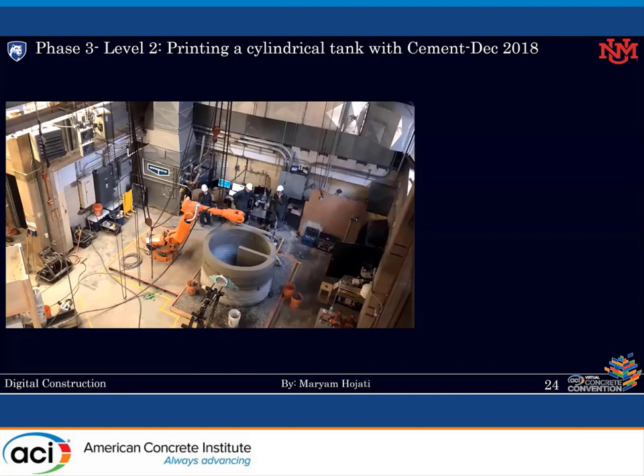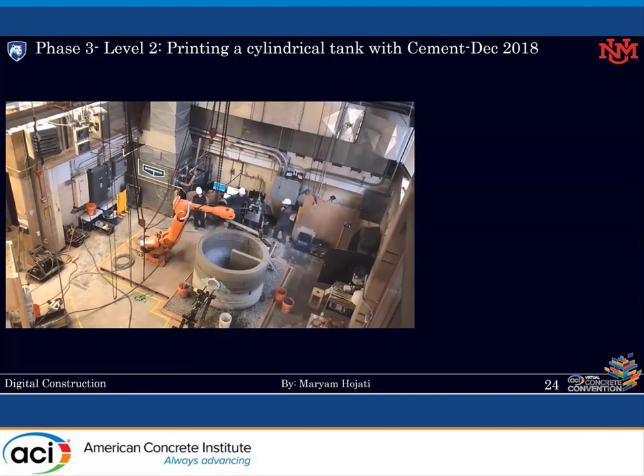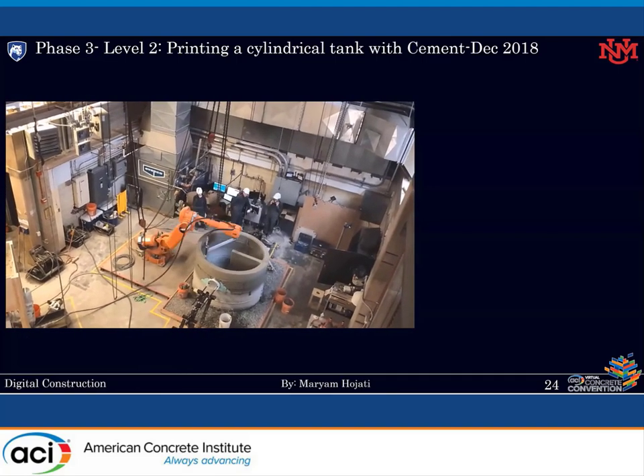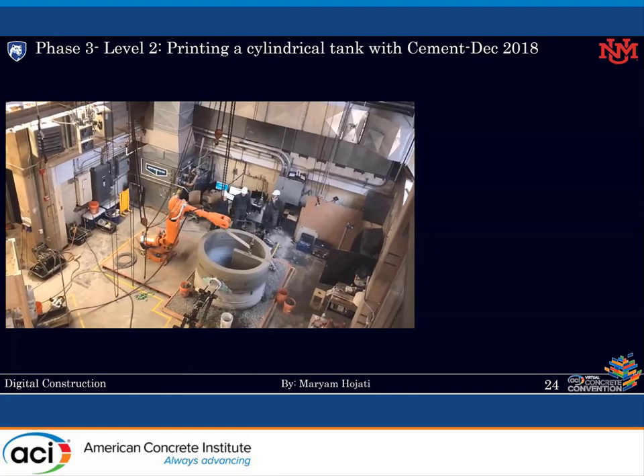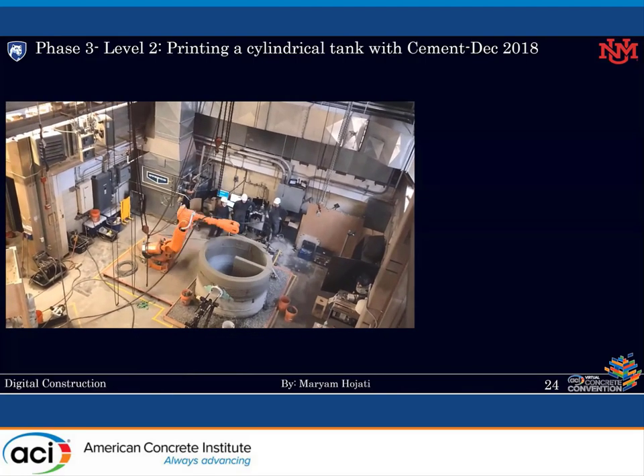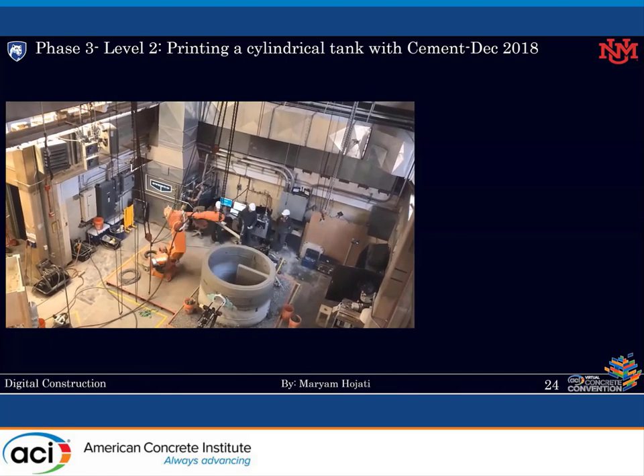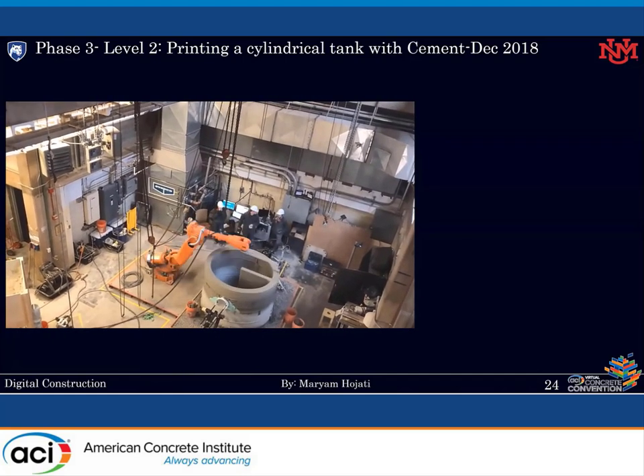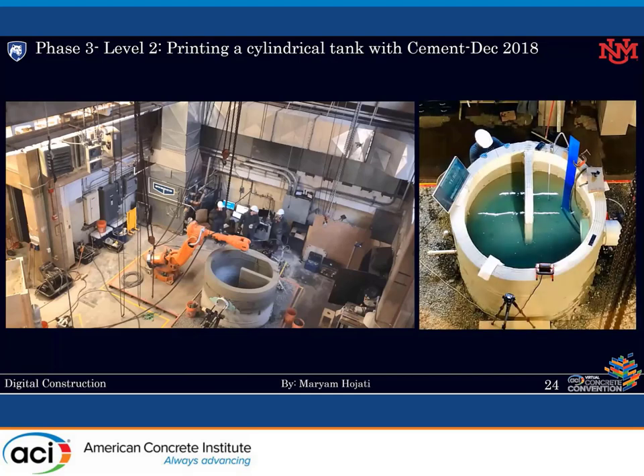The next level of NASA project was related to the 3D printing of cylindrical tank in an autonomous process. NASA asked the teams to evaluate the quality of the printing and also conduct a hydrostatic test to measure the leakage of water over 15 minutes. Penn State successfully passed this level of challenge as well. And you can see the printed tank in this slide.